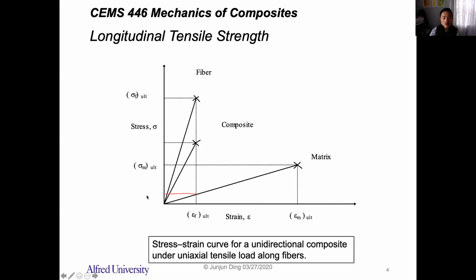So you should use the stress at this point, this stress of the matrix, to calculate the ultimate stress of the composite. So you can calculate this based on the rule of mixtures. And we know that the ultimate stress of the fiber is much higher than the matrix, right? And therefore you can increase the ultimate strength of the composite compared to the matrix.